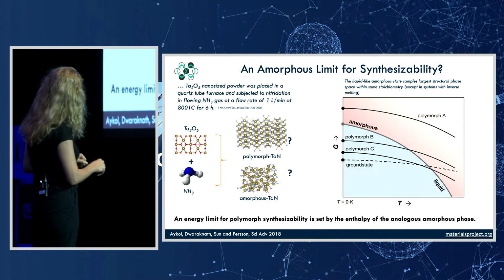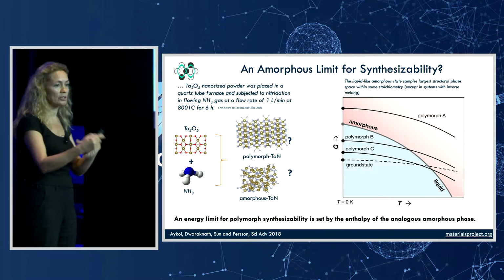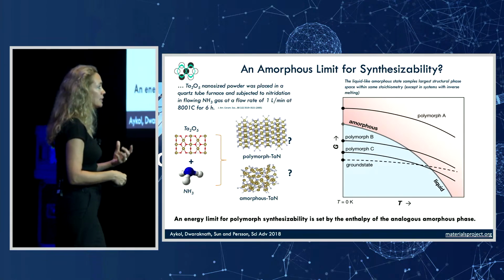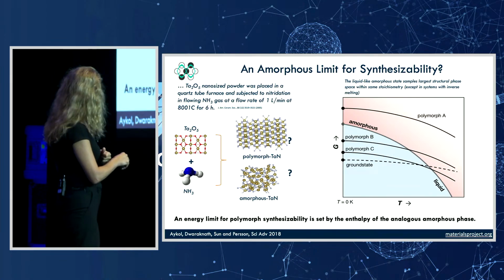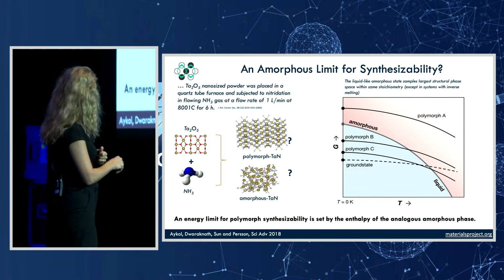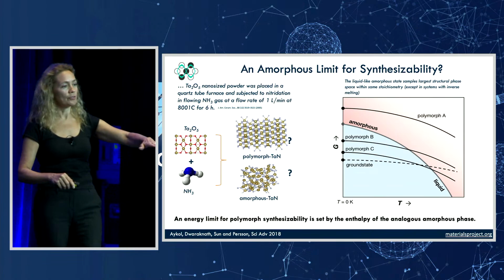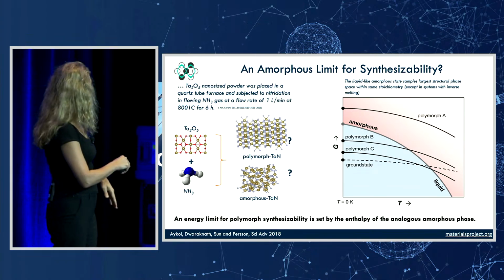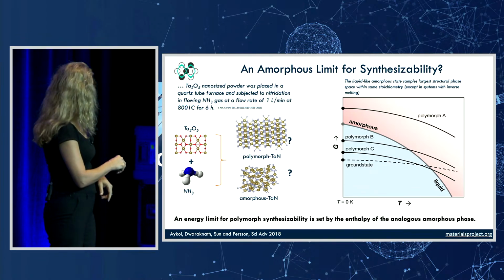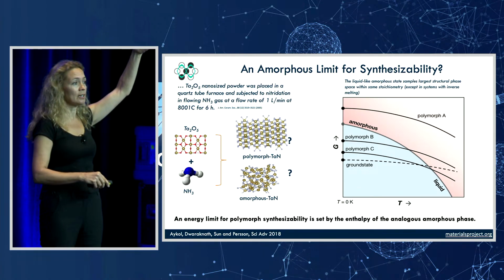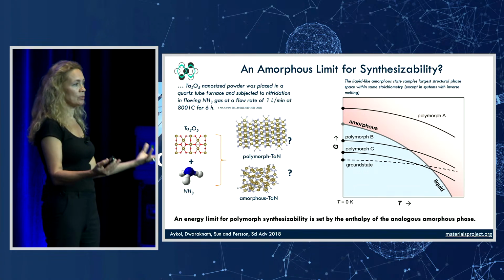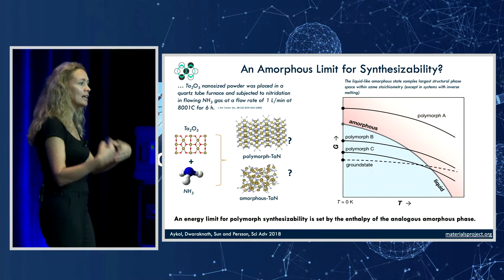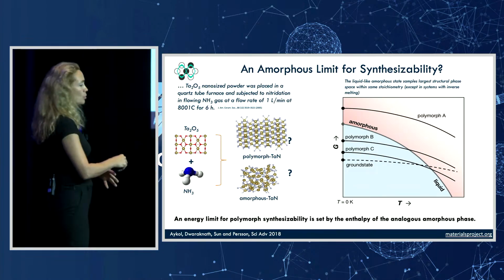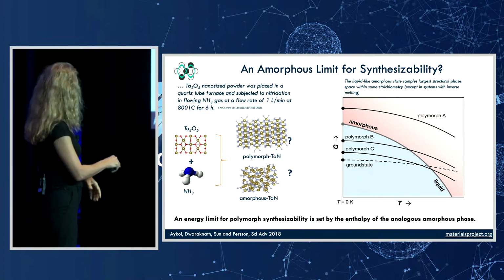And if you calculate the enthalpy of the amorphous state, we can also hypothesize or postulate that the entropy of that state is going to be higher than any crystalline polymorph because of that disorder, that configurational disorder that's much larger than any crystalline material. So the slope of Gibbs free energy with temperature is going to be higher than all the polymorphs. So let's now look at this graph here, where polymorph B and C start out with an enthalpy lower than the amorphous state. They have a window of thermodynamic stability compared to the amorphous state. But polymorph A, that starts out with an enthalpy that's higher than the amorphous state, has no window of thermodynamic driving force to form at all. So if the precursors are falling apart, they can make the amorphous state, there's no driving force for it to make polymorph A. If you're within this window here, there are driving forces to make polymorph B and C.